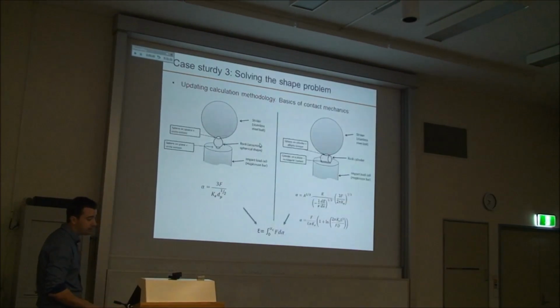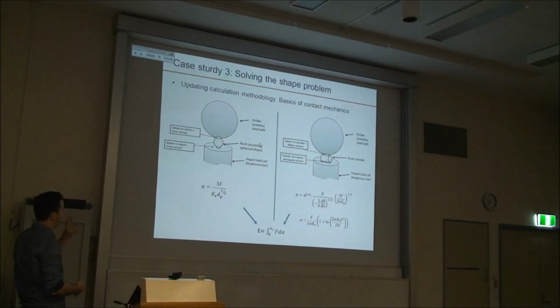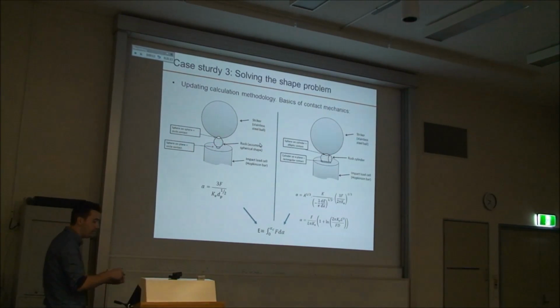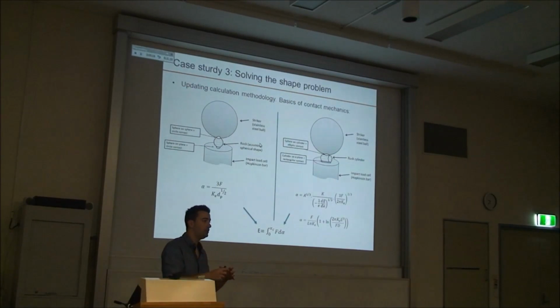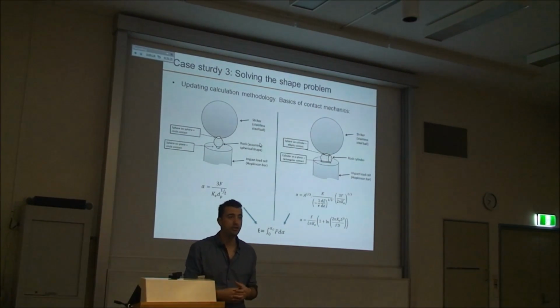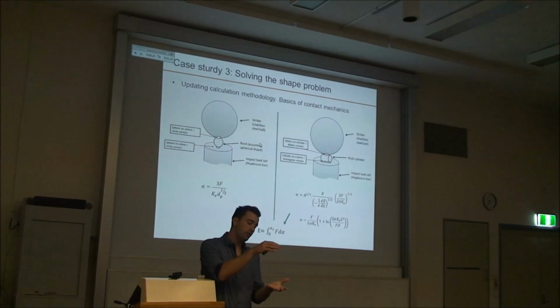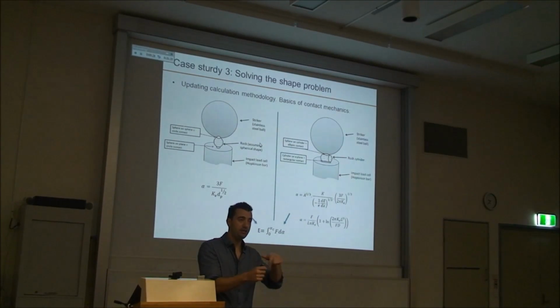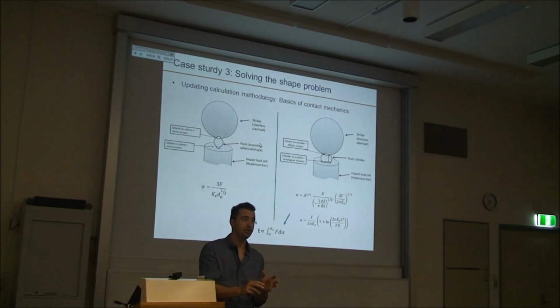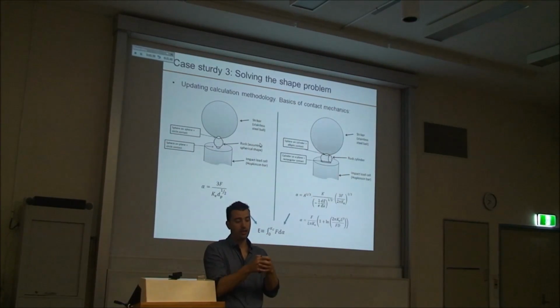And so I went on and I looked at the actual geometry of the contact. So this is on the left side, a roughly spherical particle. This is the ball falling on the particle and the particle on the bar. And the contact areas between the bar, the particle and the ball are circles. So this is based on the Hertzian contact theory. The Hertzian contact theory says that the compression and the dimension of this circle of contact is related to the force and the geometry of the particle and the ball and the bar. Okay, so this can be predicted. It's easy when it's spherical because it's a circle of contact.